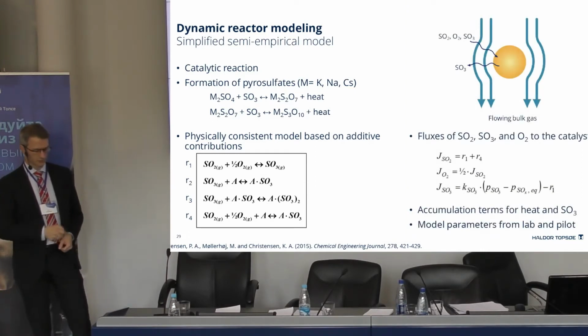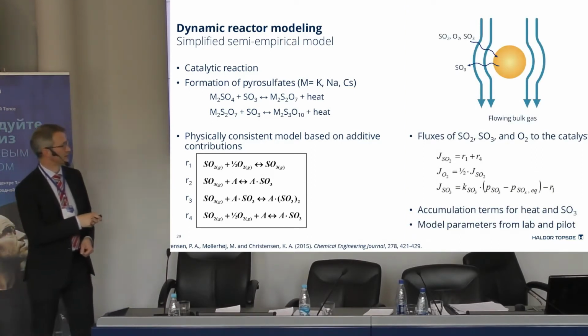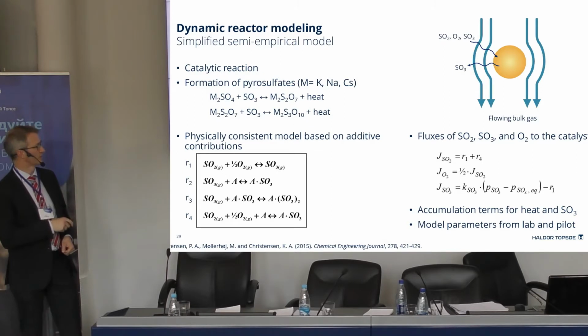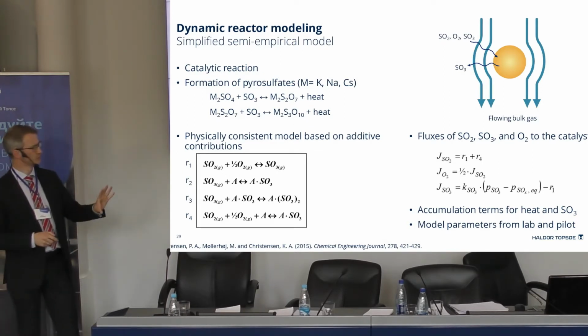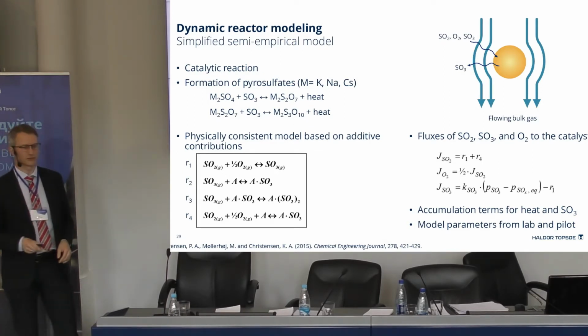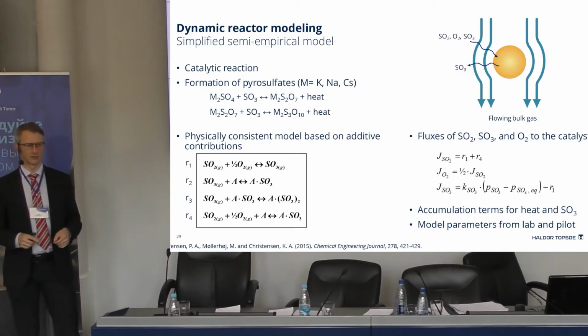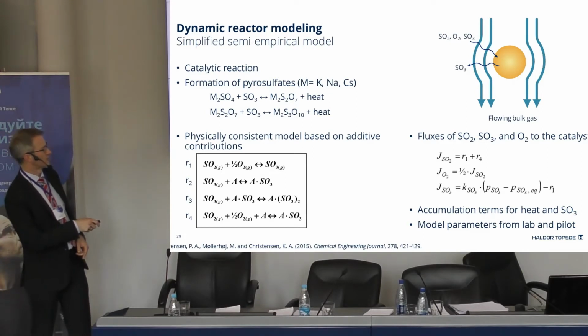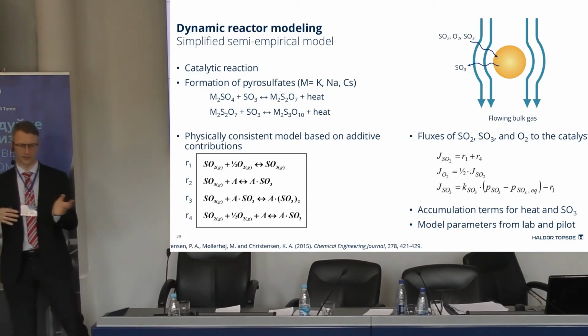The fluxes to the catalyst are given here. So the SO2 flux, that's reactions 1 and 4, they consume SO2. The oxygen follows the SO2, that's a pseudo steady state approximation for the oxygen. And then we have the last one, where we have the adsorption and desorption contribution of the SO3 going back and forth.